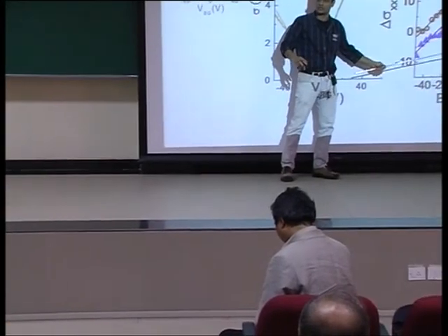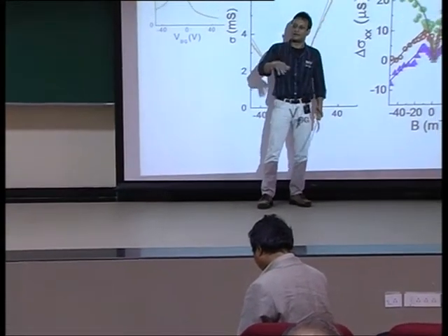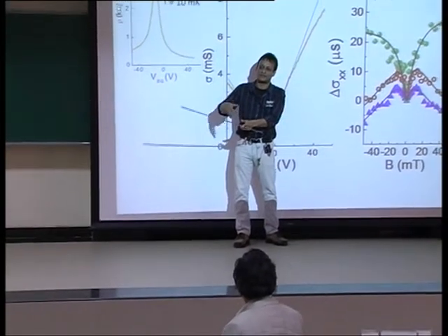You see, what happens is that at these temperatures, this is taken at 4.4 Kelvin, the weak localization correction, the negative magnetic resistance correction comes initially, and then the weak anti-localization correction takes over. So the larger field scale is anti-localization, whereas here is weak localization. This is why graphene is quite different. The quantum correction in graphene is quite different from a standard metal.